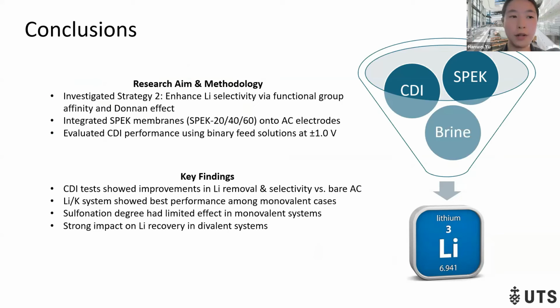Here is a brief conclusion of this research. In this research, we investigated strategy 2, which is enhanced lithium selectivity via functional group affinity and the Donnan effect. Three types of SPEK membrane were used to modify the AC electrode, and the CDI performance was tested using binary solutions. The key findings include: the CDI test shows improvement in lithium removal and selectivity compared to the bare AC electrodes. And the lithium-potassium system shows the best performance among monovalent cases. Sulfonation degree has a limited effect in monovalent cases, but a strong impact on lithium recovery in divalent cases.